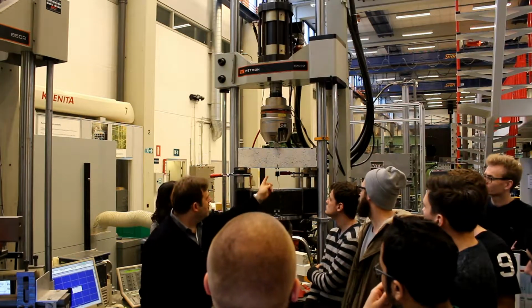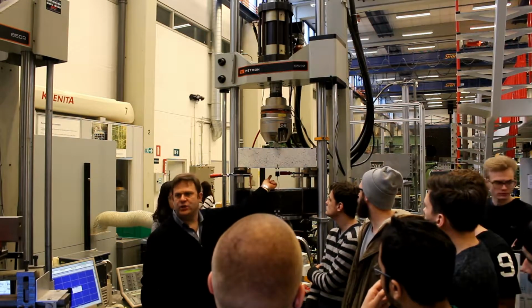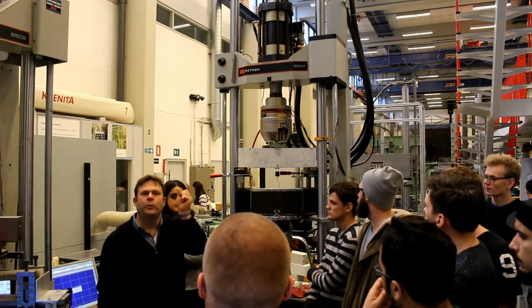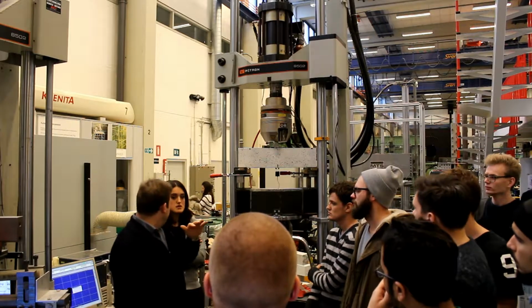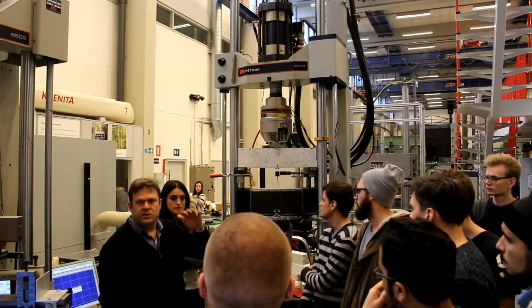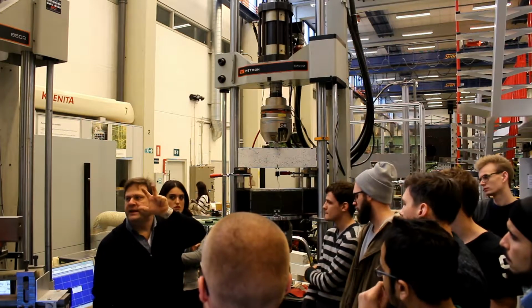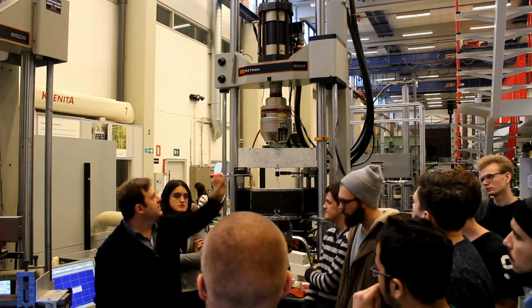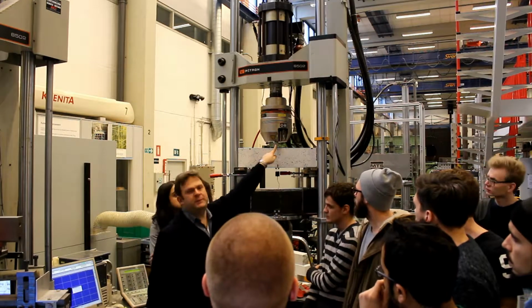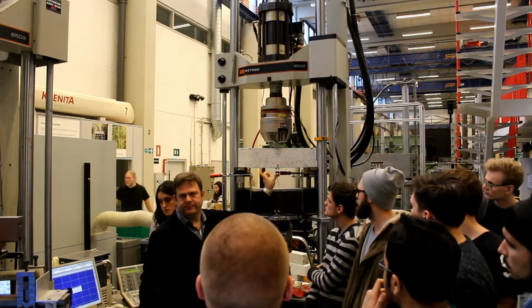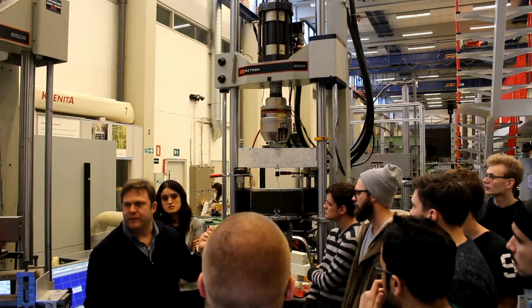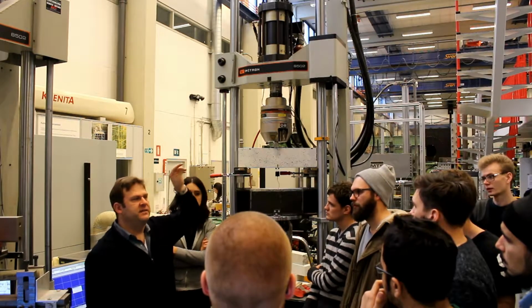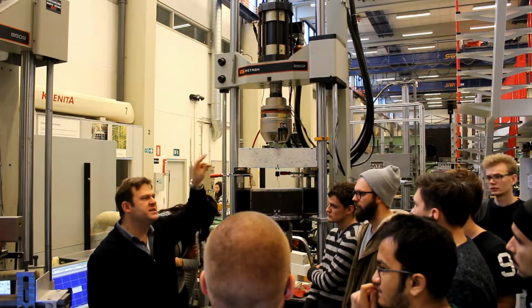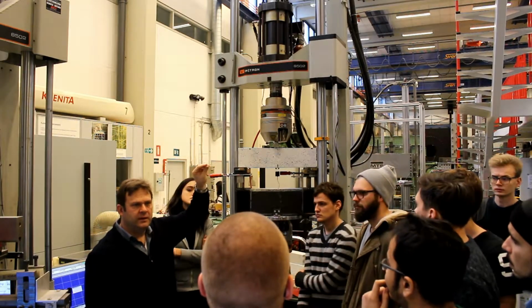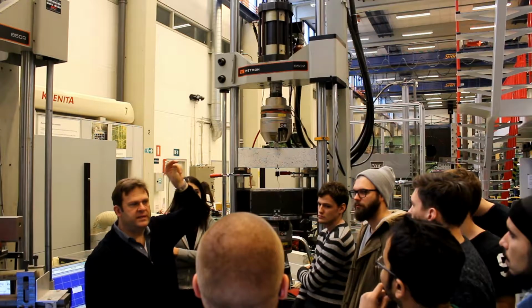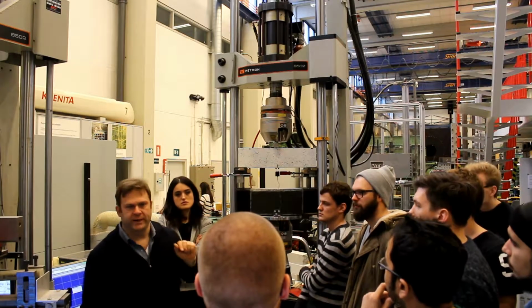We also have this additional gauge down here which will tell us the crack opening. So every tenth of a second we are reading. So 10 times per second we are reading these three quantities: load, machine displacement, and crack opening. And we get an Excel file afterwards that will tell us the time, of course, when that measurement was taken, the load, the displacement, and the crack opening.